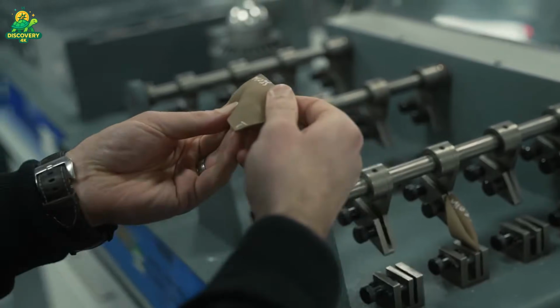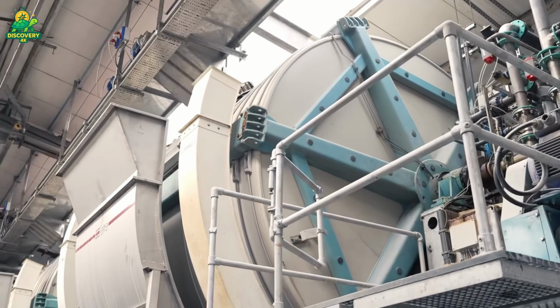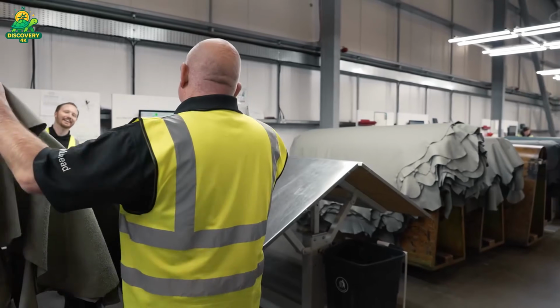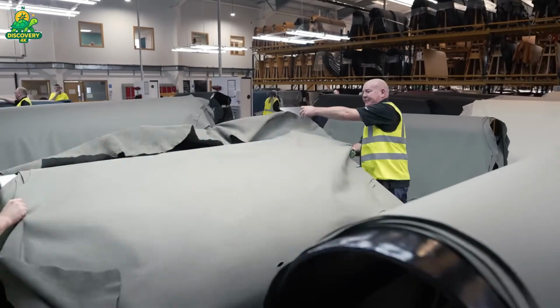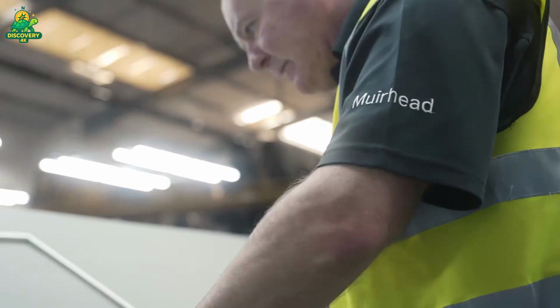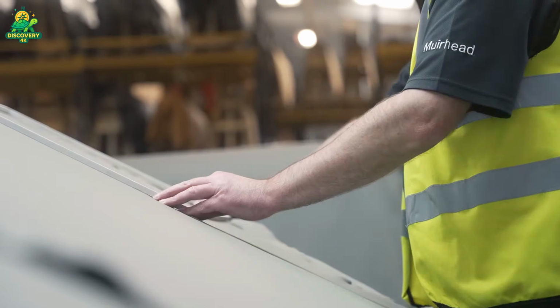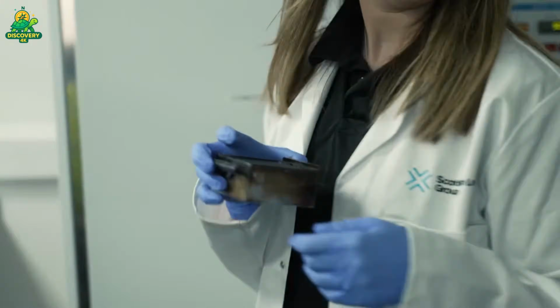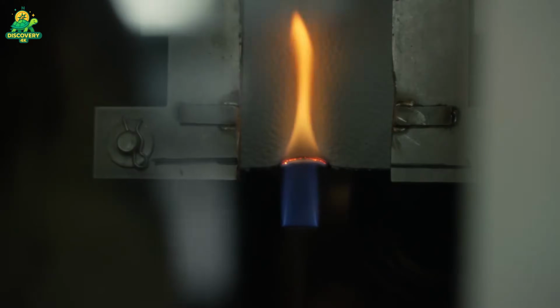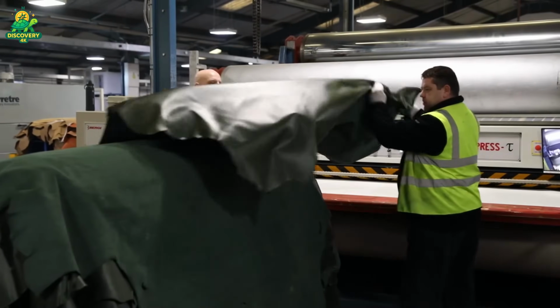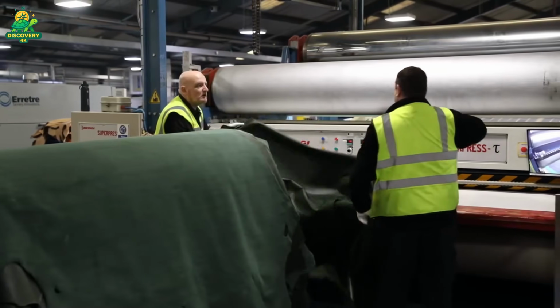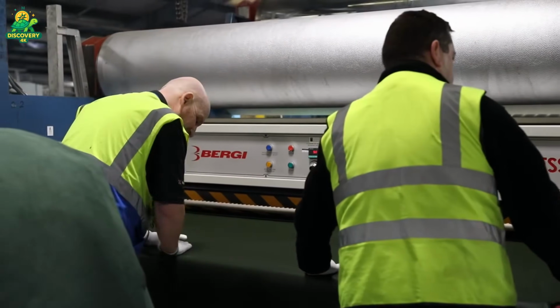After coating, the material moves through long heated tunnels, sometimes over 50 meters in length. Inside, heat and airflow evaporate solvents and cure the polymer. What was once a sticky liquid now becomes a solid, durable surface. This stage is critical. If the temperature is too high, the polymer may blister. Too low, and the layer won't cure properly, leading to poor durability.